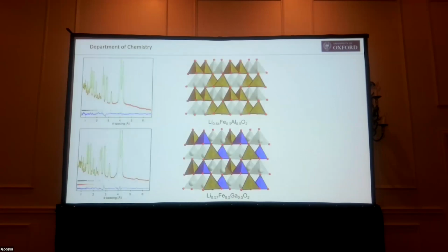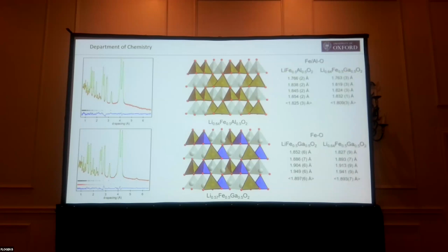So we can then look at the neutron data, the structures, and what we find is nothing remarkable. The crystal structures are retained, we just have partial vacancy on the lithium site, consistent again with our chemical analysis. And what we see, certainly in the iron aluminium case, is a slight decline in the average bond length around the iron, but in the gallium case, there's almost no change.